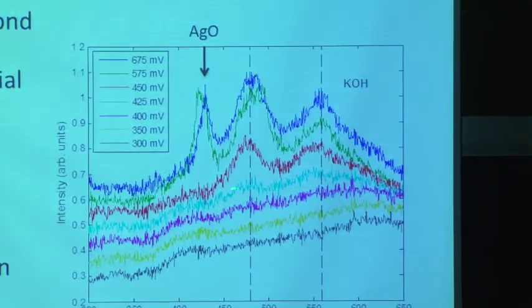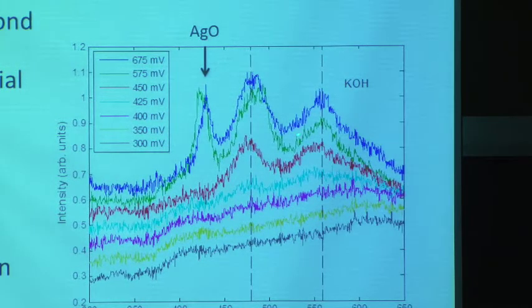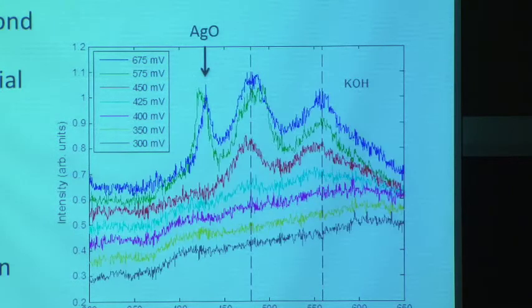Right? Now if we go to potassium, it already looks qualitatively different. You can see that these peaks form much larger. You see a very large silver oxide peak. And you start to see, let's go back one, if this peak is mostly to the right of this dashed line, as we go forward, you see it becomes a little more symmetric. That is, there are more things to the left over here. And the potential where it turns on is probably between 400 and 425.